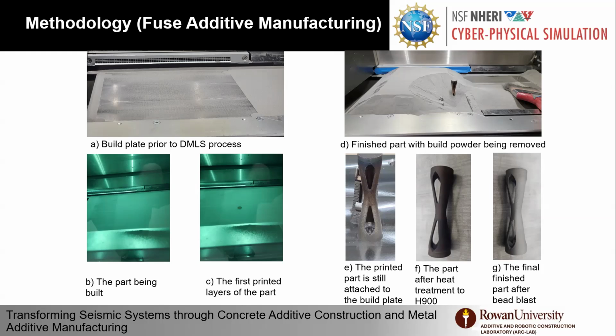On the right side, top right side, you can see here a mountain of powder that the specimen is embedded in, and you have to excavate to get the specimen out. The specimen now is detached from the build plate, undergoing heat treatment up to 900 Fahrenheit, and after that, bead blasting to make it look like steel. It is a steel, okay?